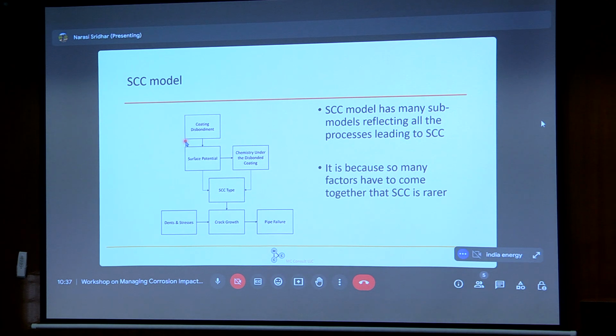So we have looked at the coating SCC model in chunks. There is a coating disbondment module. There is a module that predicts the surface potential using reactive transport modeling. There is a model that predicts the chemistry, and there are all these crack growth rate models. And the reason SCC has a low probability is because it's a Goldilocks syndrome, as they call it: all these things have to come together just the wrong way for a pipeline to suffer from SCC. That's why it has a low probability, but a high consequence.